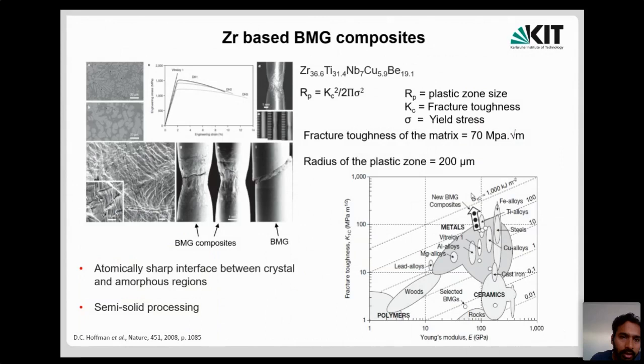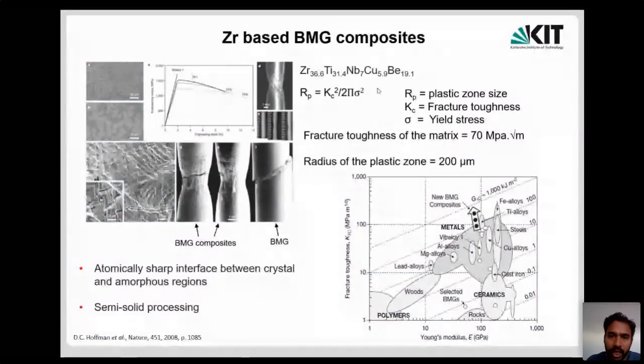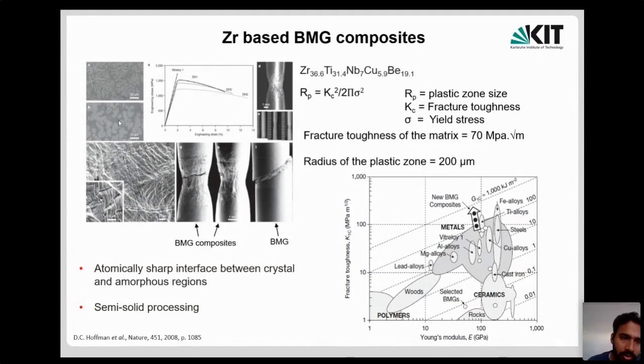The bulk metallic glass composites, and this is the composition which they have worked on. The strategy here is very simple. If you remember your fracture toughness measurements, you do by Charpy test or something, where you have this plastic zone, where you have the K_C squared by 2 pi sigma squared. And they calculated the fracture toughness or radius of plastic zone for this composition, and they found it was like 200 microns. So if you can disperse your crystalline dispersions within less than 200 microns, then the band which forms does not catastrophically transfer throughout the sample.